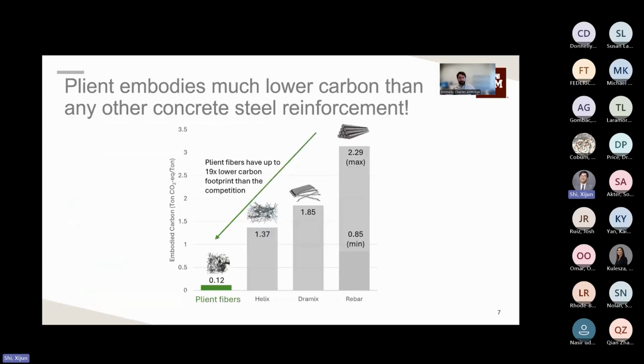I briefly touched on this, but I think this is a great plot to show: one of the key benefits of Plient is the significantly lower embodied carbon associated with Plient compared to other reinforcement alternatives. In the plot here, you see the embodied carbon, tons of carbon dioxide per ton of the material, and you see Plient, the bottom left there, is significantly lower than existing manufactured steel fiber alternatives, the two in the middle there, as well as, and this is critical, the rebar alternatives that are currently used on many projects.